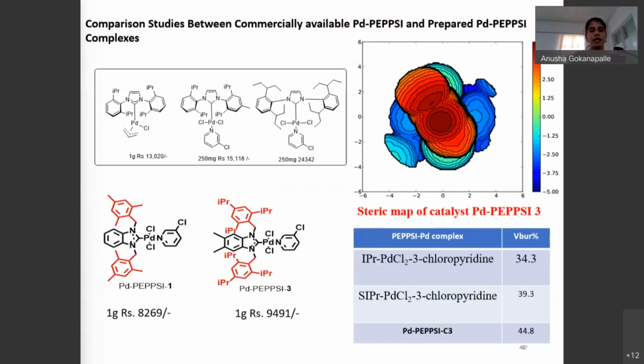Comparison studies between commercially available palladium PEPPSI and prepared palladium PEPPSI complexes. When you see the cost of commercially available palladium NHCs, 250 mg is around 15,000, but in my case, it was just 9,400. And also, this is the steric map of the palladium PEPPSI 3 catalyst. Using this map, we have calculated percentage buried volume for palladium IPr and palladium SIPr, and my catalyst palladium PEPPSI 3. Among all these three, my catalyst gave the highest percentage buried volume. Percentage buried volume is directly proportional to the catalytic activity.